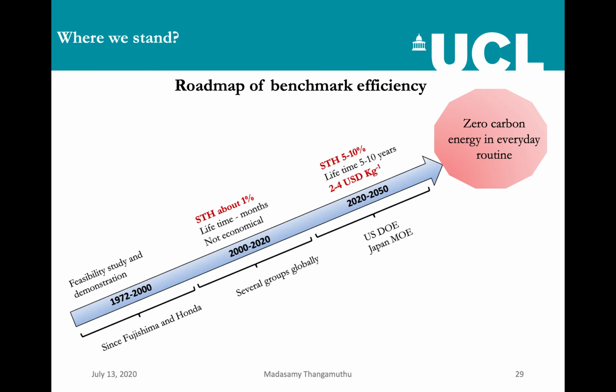Okay, so where do we stand? Same as ammonia, for like 30 to 40 years people have been working on water splitting to produce hydrogen as a fuel. But what is the maximum efficiency, or what is the breakthrough we have achieved so far? You can see from here, from 1972, the first study, they demonstrated how hydrogen can be produced from water photochemically. Recently, in the 21st century, this is again not more than 1%. In the ammonia case, it was still not able to reach 1%, but for hydrogen, we were able to produce 1 point some percent, because this is my recent work. That's a very breakthrough work. We were able to produce hydrogen at 1.7%.